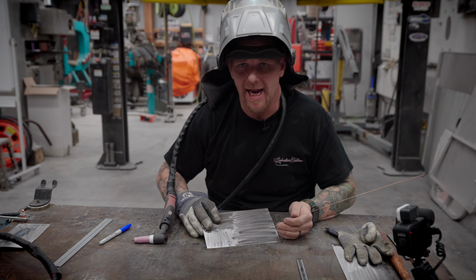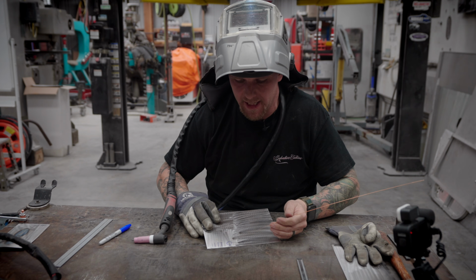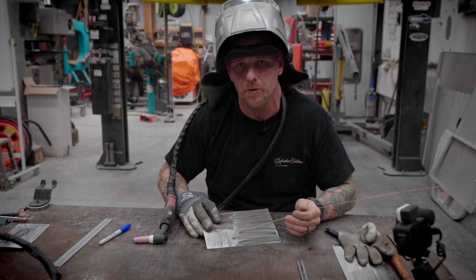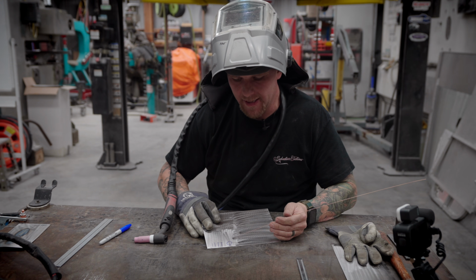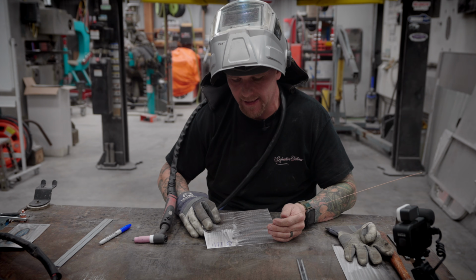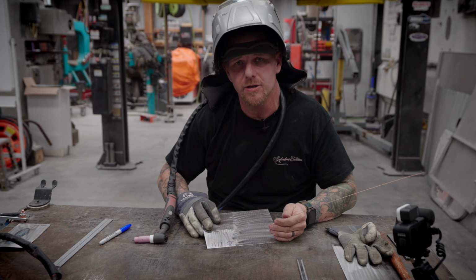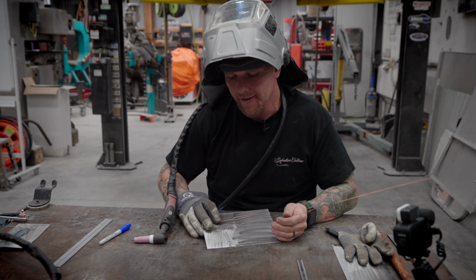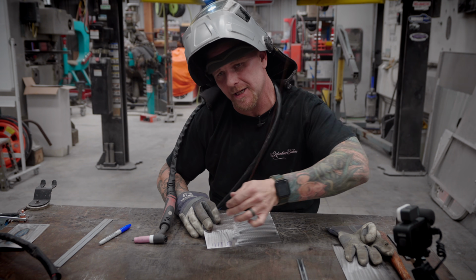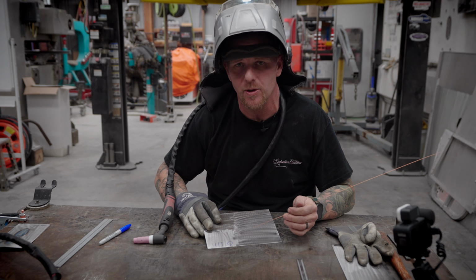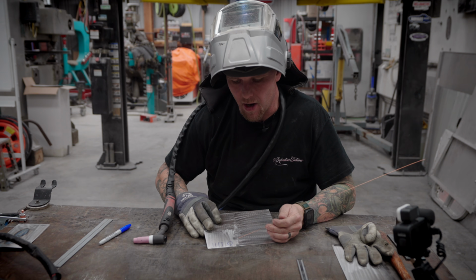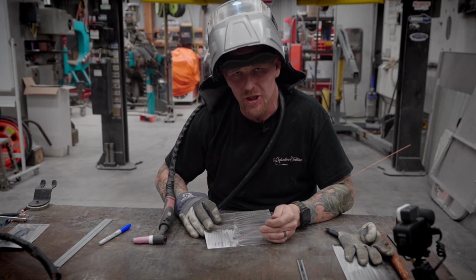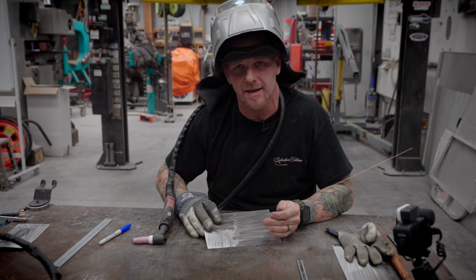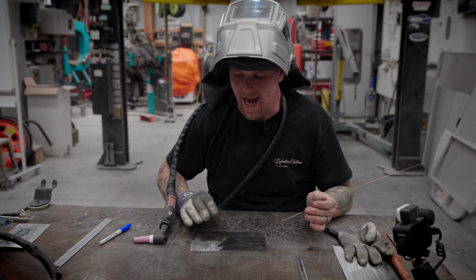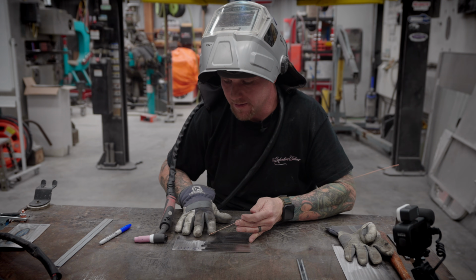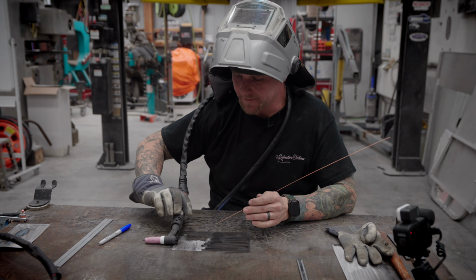What we're actually aiming for in dipping in this rotating motion, if we pretend this is the molten pool, we're coming down and we're dabbing right at the leading edge. If you hit too far in front of it, it's going to ball up and then it's going to suck it in and it's not going to look how you want it to look. We want to always aim for just in front of the tungsten into the weld pool as it starts to melt. So let's check out what that looks like.